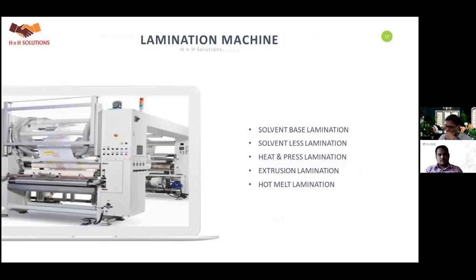Lamination process, lamination machine. Solvent-based lamination. In solvent-based lamination, adhesive and hardener, which is a curing agent or cross-linking agent, also known as isocyanate, is used along with ethyl acetate or MEK as a solvent. So we require high energy or heat energy to evaporate the solvent, and this process is normally used to produce the packing material for aggressive materials like acid, alkali, pesticides, herbicide, fungicide, insecticide, etc.